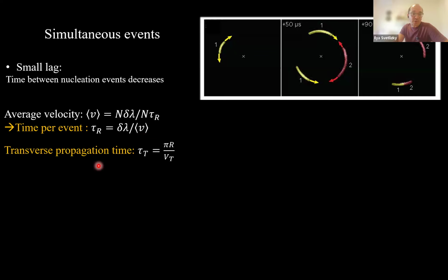Now the transverse propagation: the time for a crack to traverse half of the circle is pi r divided by the transverse velocity, which is pretty much around the Rayleigh wave speed. So you would expect simultaneous events when the transverse time scale gets larger than the time per event. And this happens when the delta lambda gets smaller and smaller. And we know that delta lambda gets smaller when the viscosity goes down. So when you decrease the viscosity, you get more and more simultaneous events.